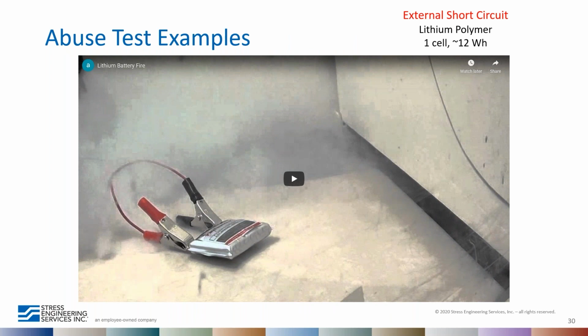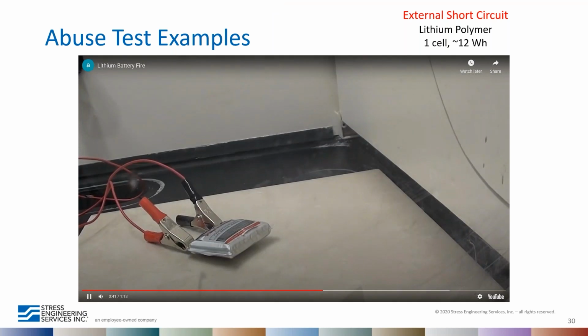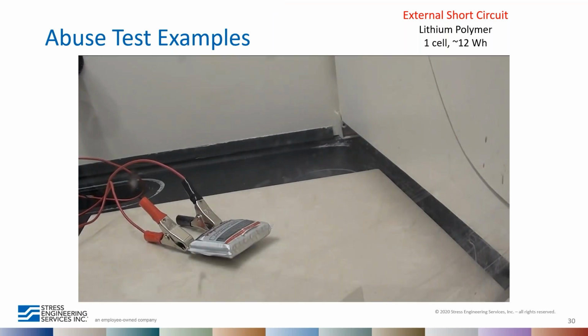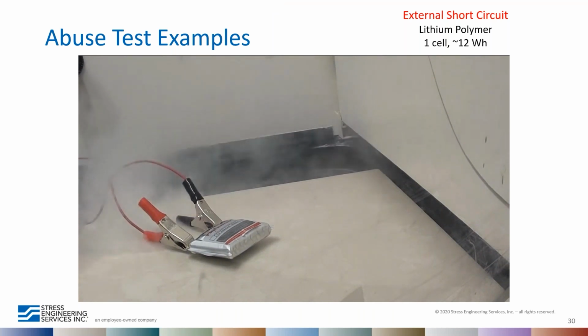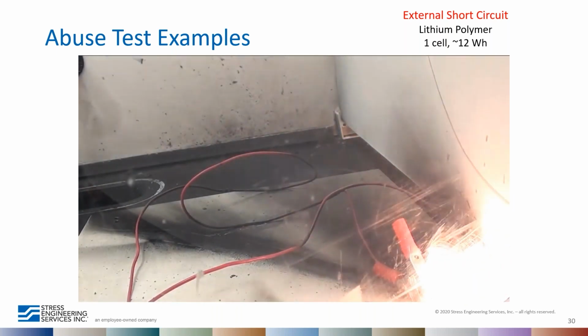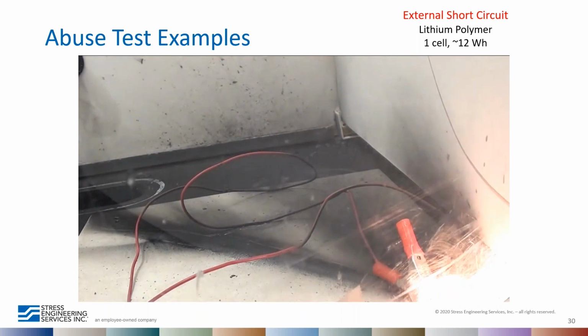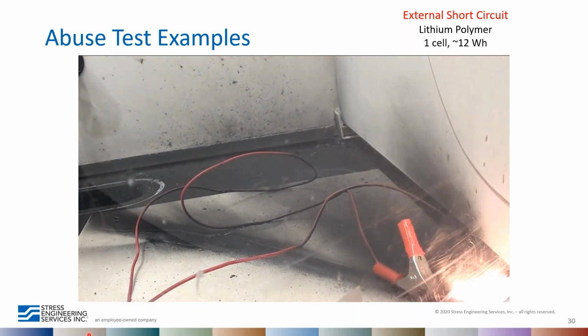All right, so first I'm going to show an example of external short circuit. This is a lithium polymer cell, and it's subjected to an external short. Typically, the external short is of a resistance that's less than the internal resistance of the battery, and that creates a worst case condition. This is driven by joule heating of the battery due to the high currents. And that heating leads to flashing of the electrolyte and eventual venting. And those electrolyte vapors combust due to the high temperature of the tabs of the cell, which leads to the large fire.